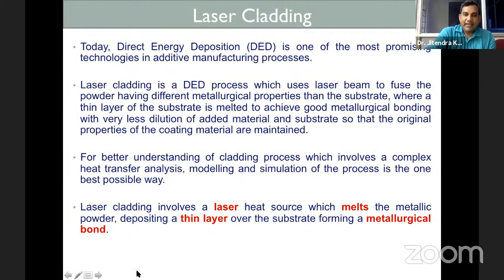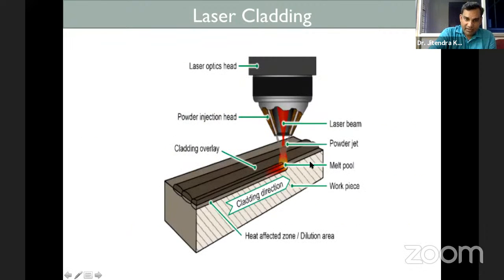So in laser cladding, you clad the surface by laser, and the powder is fed by the laser. Sometimes the laser doesn't have the facility for powder feed. Then you can spread the powder, but in that case, you will not control the concentration of the powder. So the nozzle is very, very important, how you design this nozzle. The powder is spread through this nozzle, your laser beam also passes, and this can solidify over the surface. That is called laser cladding.